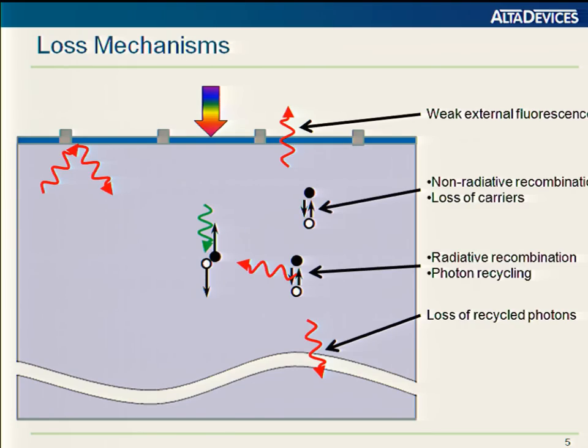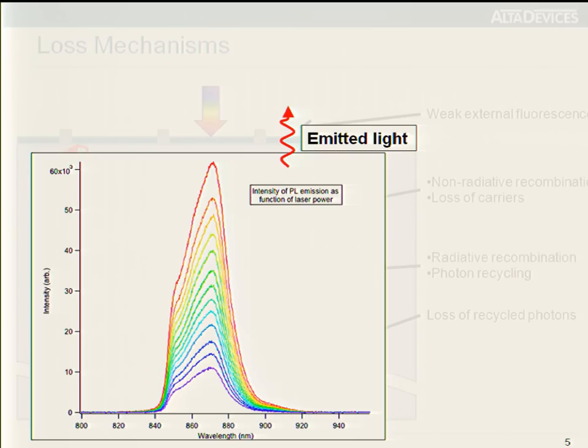So the light that you do absorb generates electron-hole pairs. These can be either collected by the p-n junction and generate current in the circuit, or they may recombine either radiatively or non-radiatively. For the materials we work with, single crystal gallium arsenide, the internal fluorescence yield is very high, 98 or 99%. That means of all of these recombination events, 1 in 50 or 1 in 100 is non-radiative. The vast majority are radiative recombination events, which means a band-edge photon is emitted during this recombination.